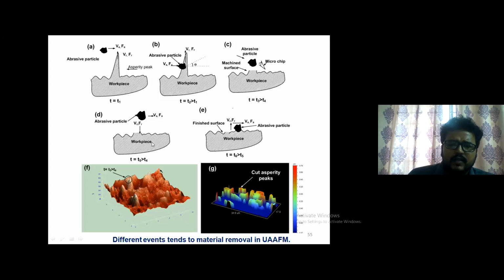So in another figure with the validation, you can see, say for example, this is a workpiece and this is an asperity and this is an abrasive particle. So the asperity peak is hit at an angle theta. So with vibration, with respect to time, you can see the different levels of a sinusoidal cycle when it is rising and receding. And in another case, you can see atomic force microscopy of the finished sample.